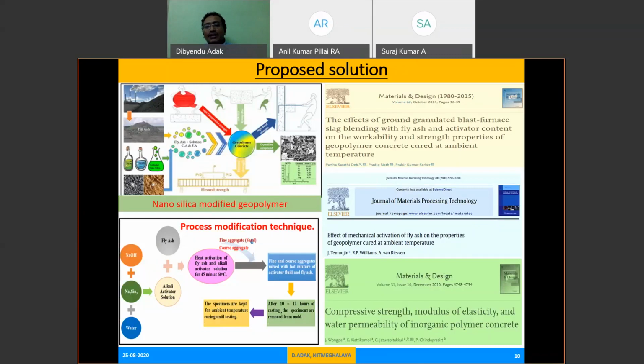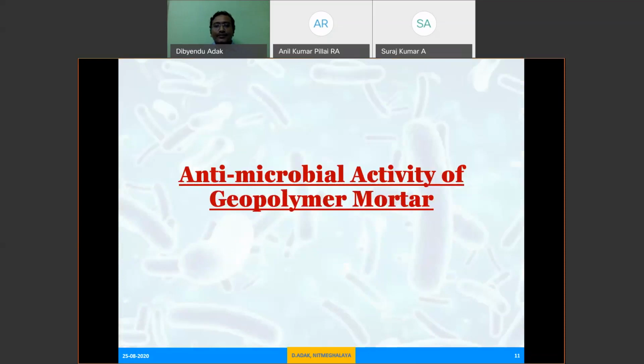Other than this, if you add ground granulated blast furnace slag, the calcium content is higher. The calcium and alumina content will also reduce the setting time, so we can get the geopolymer concrete at normal temperature. Other than this, if we activate the fly ash in a ball mill and reduce the fly ash size to 1/10 of the normal conventional size, then as the size is very small, it has a higher rate of polymerization. These are the techniques proposed to eliminate the heat activation process for geopolymer concrete. Now I will come to the topic of antibacterial activity of these fly ash-based geopolymer concrete.